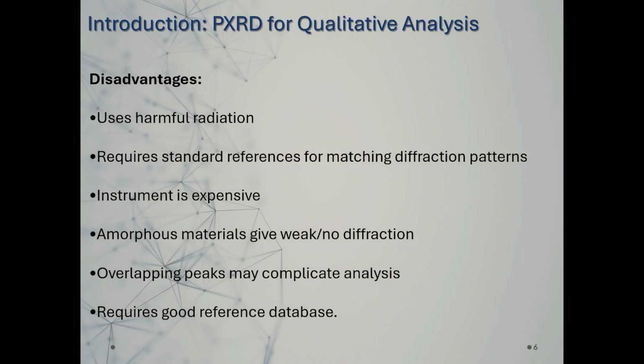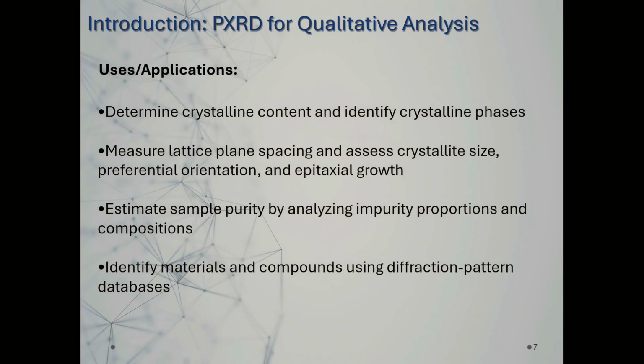Of course, there are also some disadvantages. As I said before, there can be samples that are really sensitive to X-rays. It requires standard references for matching diffraction patterns. To acquire the machine, an X-ray diffractometer is quite expensive, and amorphous material can give, as we already have heard here, a weak signal or no diffraction, and overlapping peaks can complicate the analysis, and in the end, we require good reference databases. The uses of qualitative phase analysis are to determine the content of crystalline samples, to measure and assess the crystallite size, to assess preferred orientation and epitaxial growth, to estimate the purity of a sample, and to identify new or known materials by using X-ray powder diffraction with a known database.